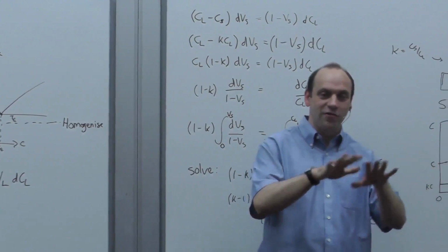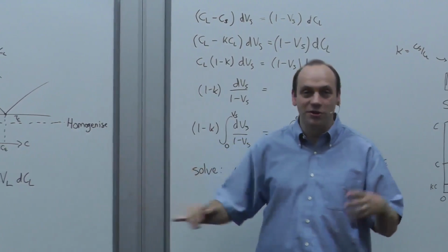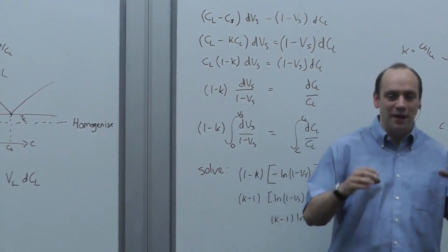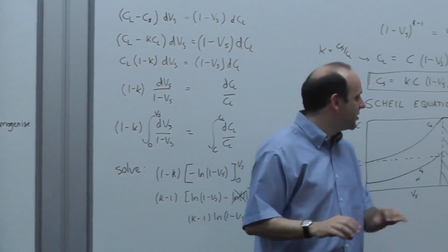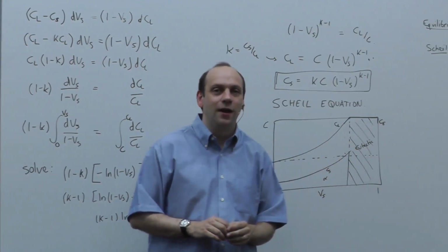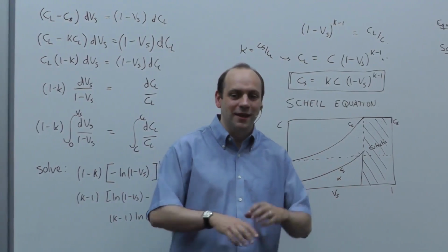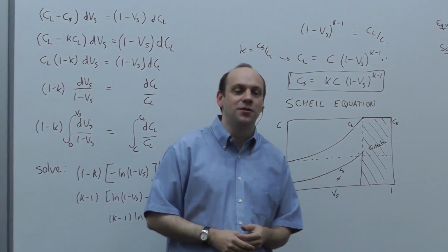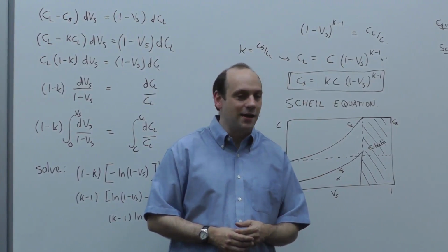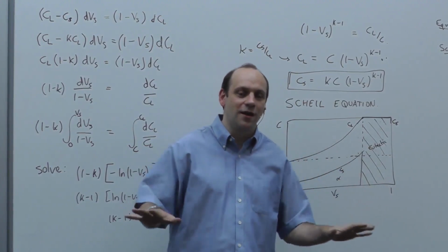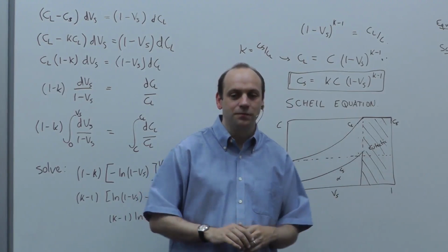You get rid of all of the structural variations. And that's what a homogenization heat treatment is. It's where you're equalizing the composition everywhere in our micrograph, in our dendrites, getting rid of that eutectic, getting rid of the variation in composition through the solid, and getting to a situation where all of the solid has the same composition.